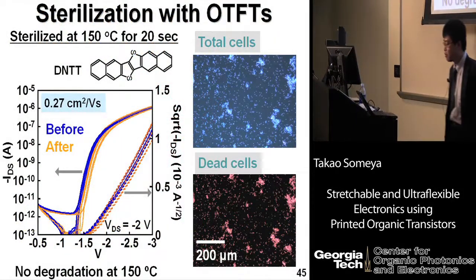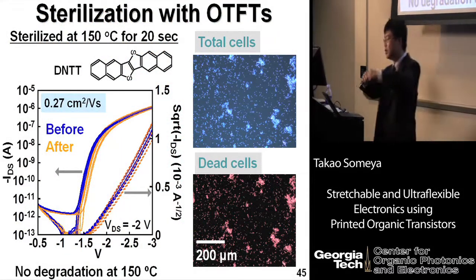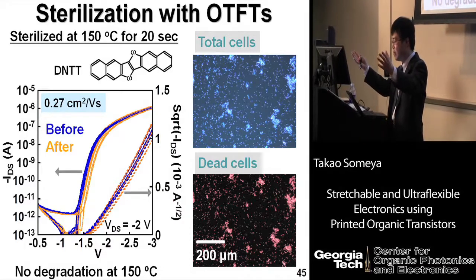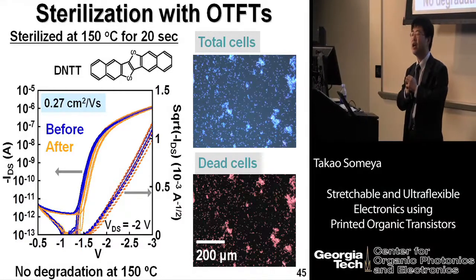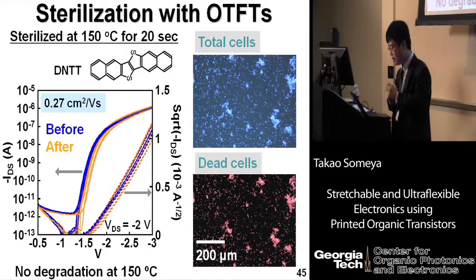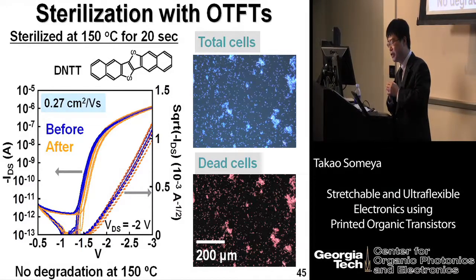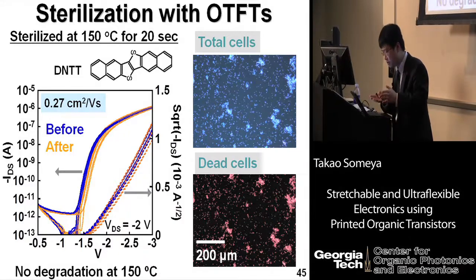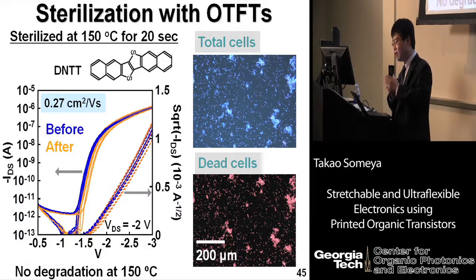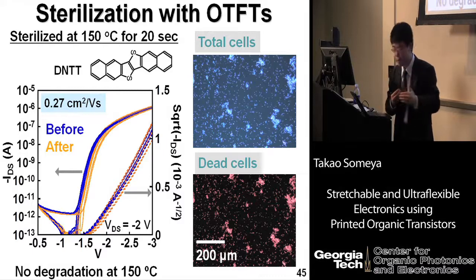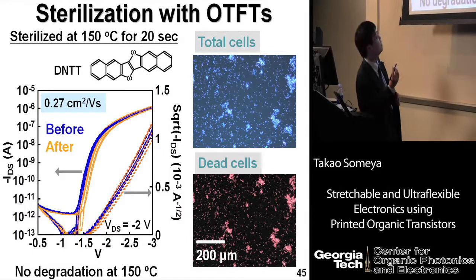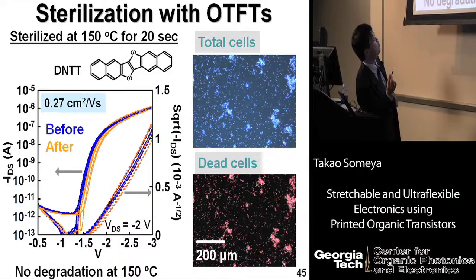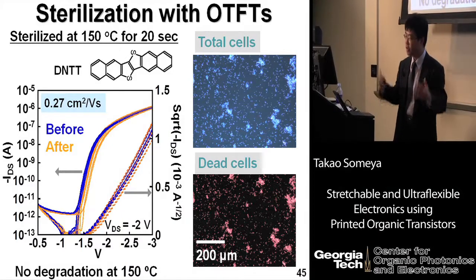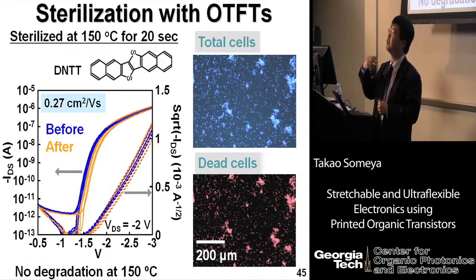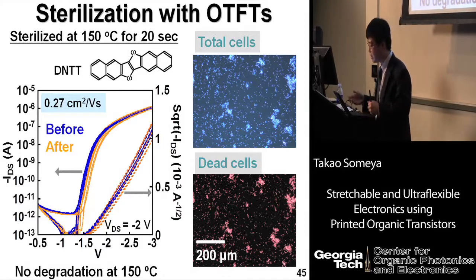The experiment was quite straightforward. I distributed bacteria on the surface of the organic transistor and then annealed it at 150 degrees Celsius for 20 seconds. Now all the bacteria were killed, but the important thing is that the electronic performance of the organic transistor didn't change at all. So in this way we succeeded in sterilizing the organic transistors.